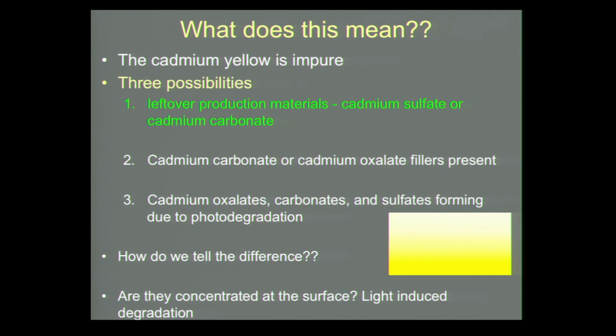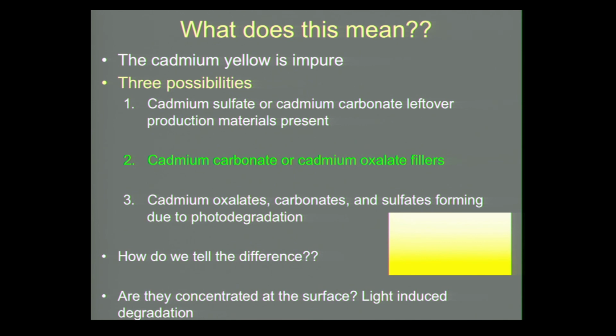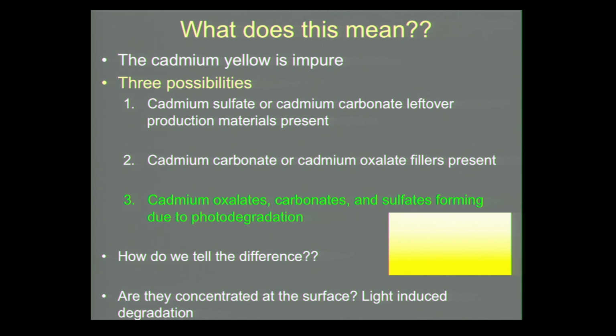So what does this mean? It means that the cadmium yellow is impure, and there's really 3 possibilities in terms of what could be going on. The first is that we're looking at leftover production materials. So there's cadmium sulfate or cadmium carbonate that's present in the paint as a result of how the paint was produced. The second possibility is that we're looking at fillers that the paint manufacturer added to the paint, such as cadmium carbonate or cadmium oxalate. And then the third possibility is that the paint is filled with cadmium oxalates, carbonates, and sulfates as a result of photodegradation. So how do we tell the difference between these 3 different possibilities? Well, we really have to look at where these different compounds are located within the paint layer.